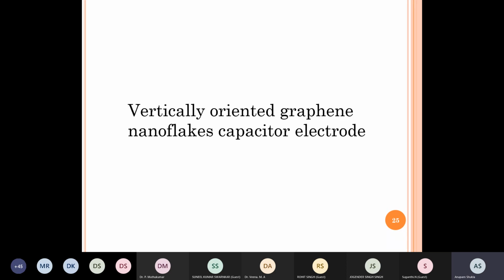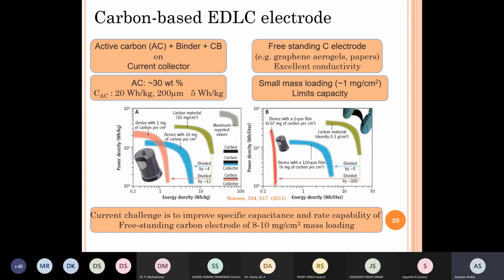The first glimpse is titled vertically oriented graphene nanoflakes capacitor electrode. If you look at a carbon-based EDLC electrode, we have active carbon plus binder plus carbon black, which is a conductivity enhancer, on a current collector. This is what an electrode looks like. Usually the composition is that the activated carbon is about 30% by weight. An activated carbon can provide an energy density, based on its capacitance of about 100 farads per gram, of 20 watt-hour per kg, provided that the thickness of the electrode is 200 micron.